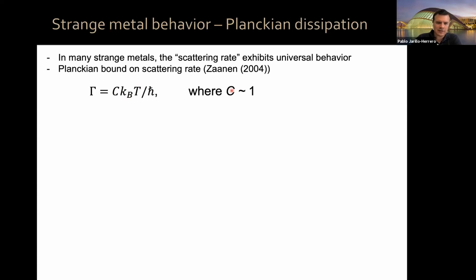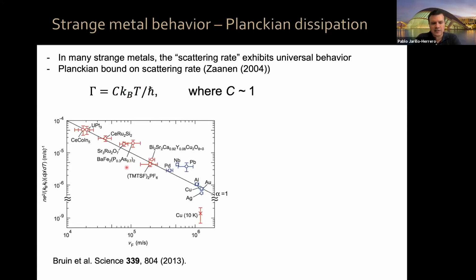So this is something that was investigated in many materials, and put together very nicely by the group of Andy Mackenzie. It's a complex way of showing it, but basically this straight line here is telling you the Planckian scattering rate, and you can see that many correlated materials have a scattering rate roughly on that edge, in that range. Also, a number of uncorrelated materials at high temperatures exhibit that behavior. Copper at high temperatures, for example, but not copper at low temperature.